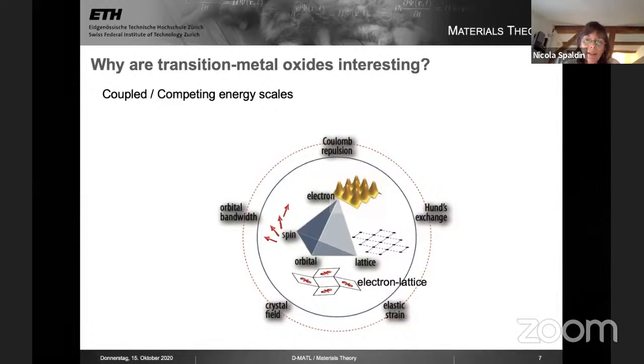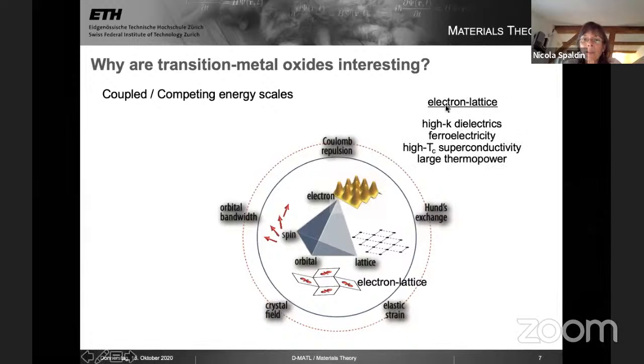transition metal oxides. So for example, the coupling between the electrons and the lattice manifests in very large dielectric constants. If I apply an electric field, the system will polarize a lot because there's a strong interaction between the electron and the lattice. Also ferroelectricity, which we'll come back to, and large thermopower, so good thermoelectric behavior. And I guess it's a little bit controversial, but high-TC cuprate superconductivity probably also certainly has an electron-lattice interaction component.